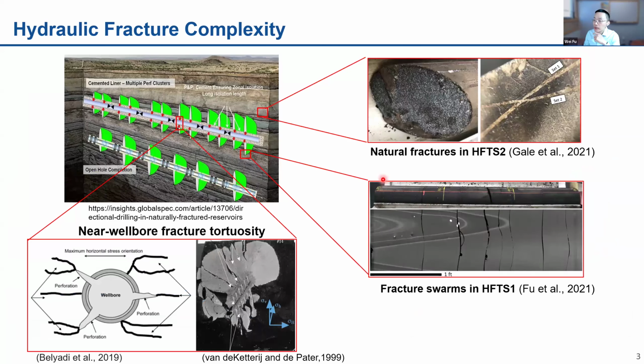So here, I'm gonna use a simple sketch of hydraulic fracturing in multi-stage horizontal well as an example. So instead of homogeneous media, the subsurface can be inherently heterogeneous with various discontinuities, such as different joints, bedding planes, and sometimes big faults. And here's a plot of the natural fractures in the HFTS2, the hydraulic fracturing test site in the Midland. So these are retrieved cores, which shows the sketches of the natural fractures on the interfaces. And these are calcite-filled natural fractures in the core samples joining each other.